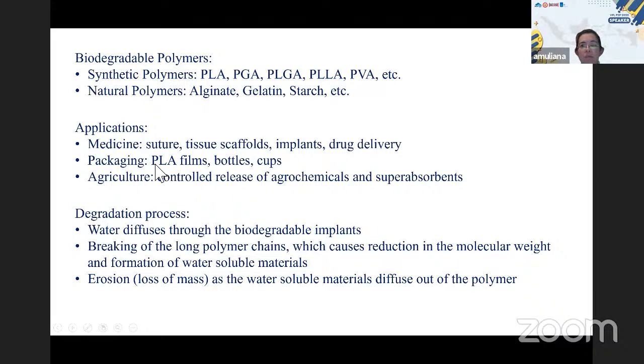So, what is the degradation process? Why do we call it biodegradable? The degradation is through hydrolysis, meaning it needs an aqueous environment. It starts with water diffusing through the polymer body. So there is a reaction, right? That induces scission, meaning a breaking of the polymer chain. So the long polymer is now broken into smaller chains. And if this breaking continues, it will lead to the formation of what we call water-soluble materials, right? These water-soluble materials can diffuse out of the polymer body. This is what we call erosion. During erosion, you would notice the polymer undergoes loss of mass, while during the diffusion, you would notice that the polymer has a mass gain, right? And somewhere in between, there is the hydrolysis process.